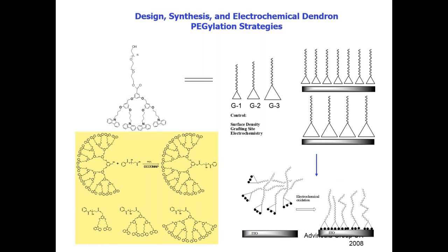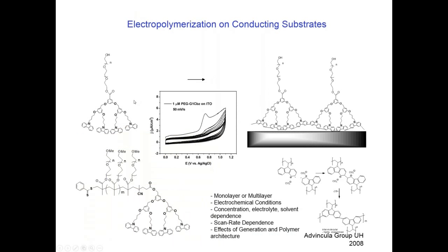We focused on a family of polymers called linear dendron systems, where we can vary the distance between these PEGylated linear chains by controlling the size of the anchoring group. As shown here, the bigger the anchoring group, the higher the surface. Synthetically, we made these carbazole-containing dendrons with a PEG or a TEG oligomer group, and then deposited them on the surface by electropolymerization. So in principle, we can have varied distances between this TEG depending on the anchoring group.